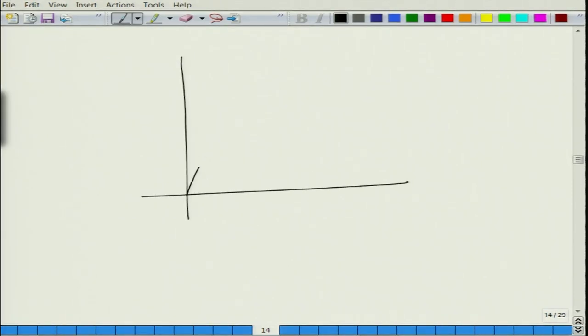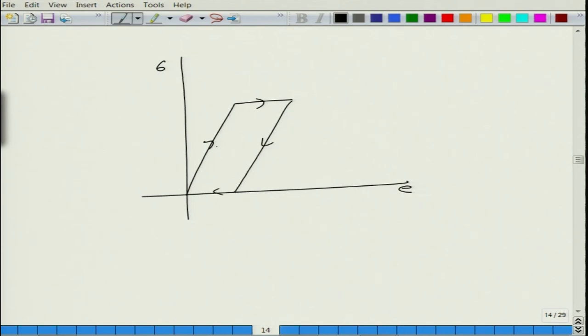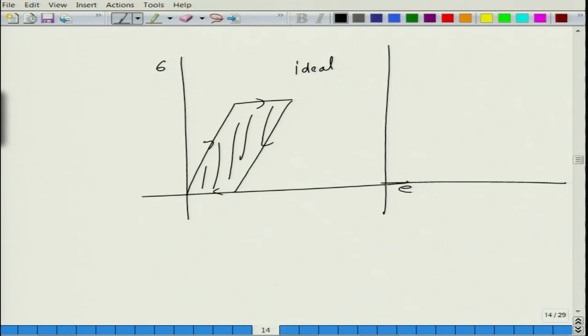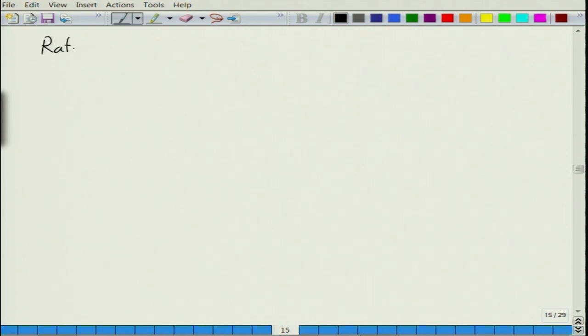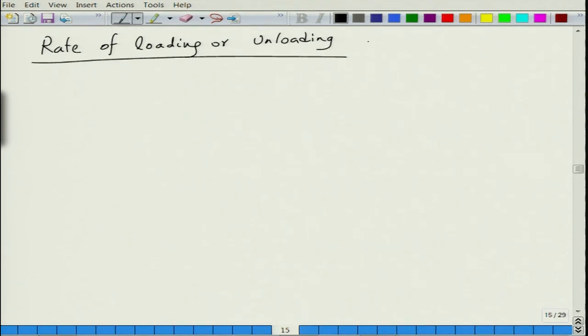This kind of hysteresis — in an ideal world you will see a certain loop. There will be some energy dissipated, but in reality what we see is something slightly different. This is sigma_max; correspondingly you have E_i, and this is the energy that is dissipated in the process of loading and unloading. This energy dissipated is essentially dependent upon the rate of loading and unloading, and the energy dissipated shows a bell-curve behavior as a function of frequency.